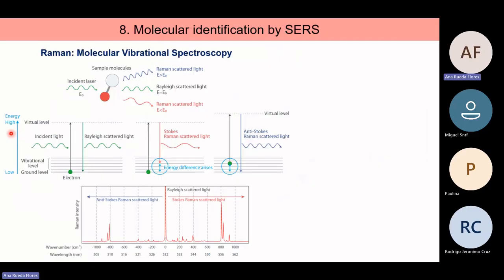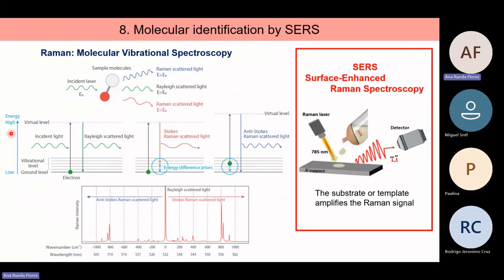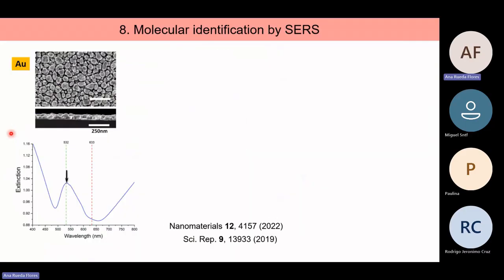But as less than 1 part per million of the light is suffering this scattering, you need to amplify the signal. One possibility is to use a corrugated metallic surface, and you can take advantage of the localized surface plasmon resonance of the template. For this experiment, we were using the gold vertical nanopillars, and you can see the extinction spectrum here, which exhibits a peak for the wavelength in the green. So if we use a green laser, we will excite the localized surface plasmon resonances of these gold nanocolumns.